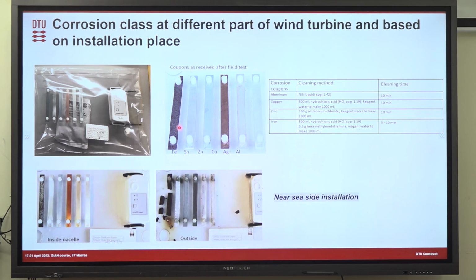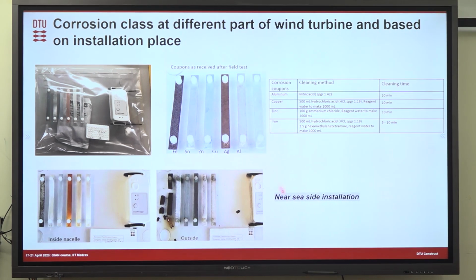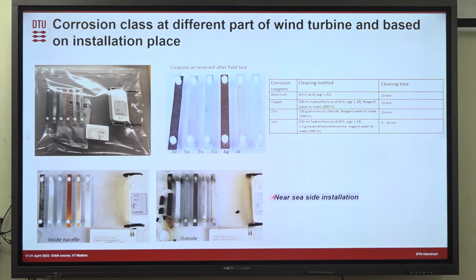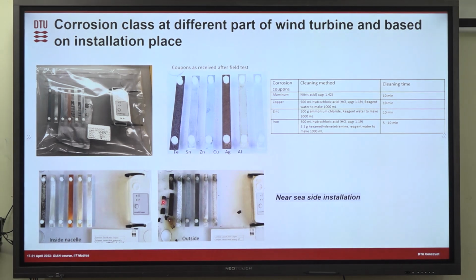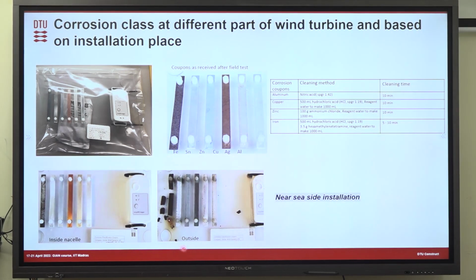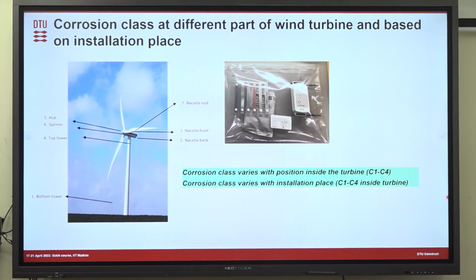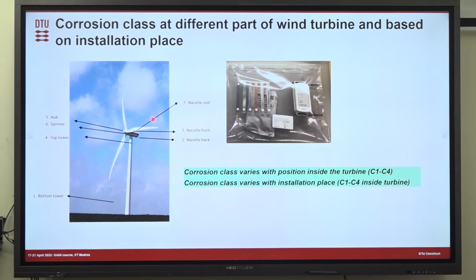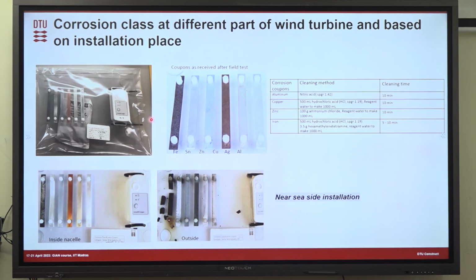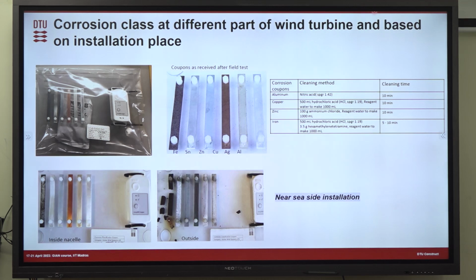So you can see that these coupons are corroded. And you can see that this is one of the seaside installations, in this case a coupon that is outside. Outside means it was on the nacelle roof or hub, where it is directly exposed to the environment, and you can see that the steel is almost completely corroded and broken. So these different levels of chloride, we can quantify.